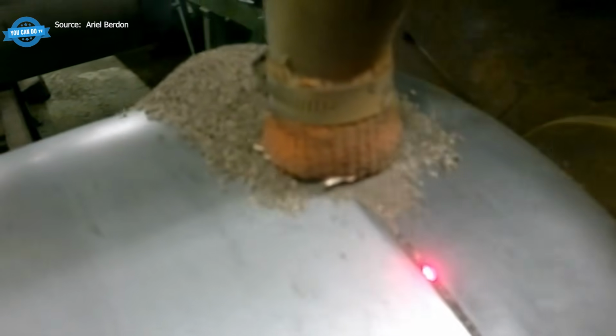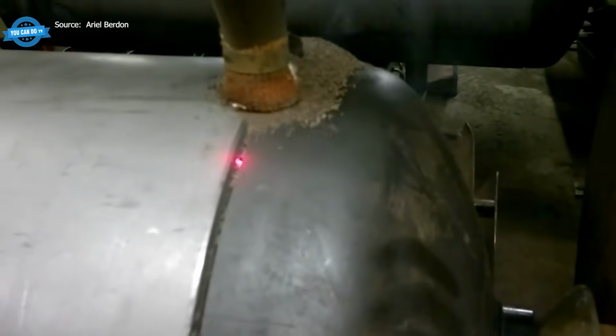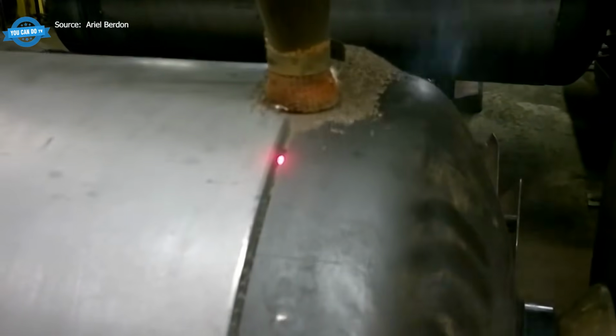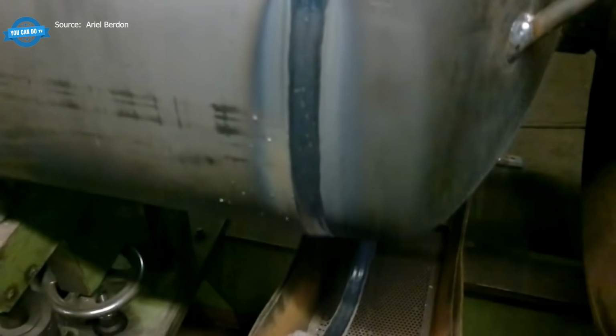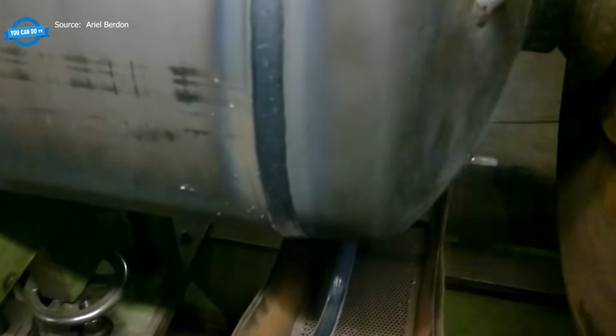The same submerged arc principle is used wherever a structural weld has to be both deep and consistent. A pressure vessel rotates on driven rollers, while a stationary welding head lays down the seam. Flux covers the arc. The slag is later chipped away. The exposed weld underneath is smooth, even, and uniform, qualified to carry pressure across the full design life of the vessel.